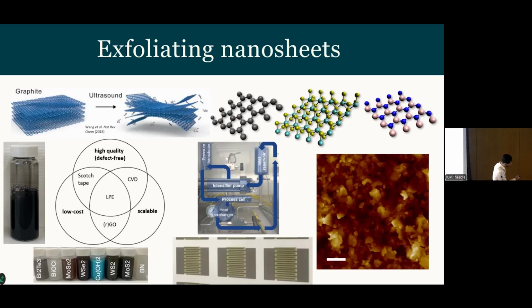But we can have things that are large, bulky flakes, or we can select down to smaller but very few layer material. We characterize those typically with Raman mapping. So we map the Raman spectrum across the ensemble, and we get very good representation, which is more challenging with microscopic techniques. And we also see, as we increase the centrifugation speed or time, the Raman spectrum, particularly the 2D peak, starts to look more symmetric, like the monolayer graphene. And we do find few layers and monolayers in a lot of these dispersions at the small end.